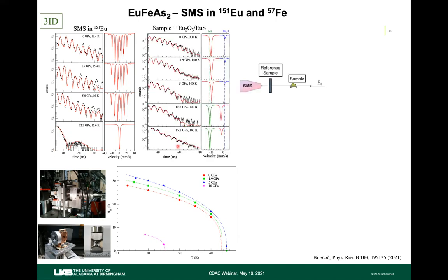And then we also measured the isomer shift by placing a europium standard, either europium oxide as a 3+ standard and EuS as a 2+ standard, because at higher pressure we noticed that with increasing pressure, the isomer shift, shown in this red curve here, is actually moving toward 0, toward the 3+ standard.